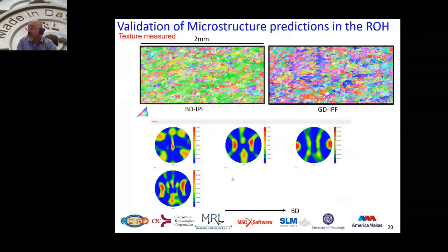And now this is how the measurements of the texture look, to show you also the micrographs, the inverse pole figure maps and the measured microstructure that we were comparing with the predictions. And I wanted to confirm to everybody, we are not predicting the spatial information about the IPF map. We are predicting the ODFs to represent the texture information.